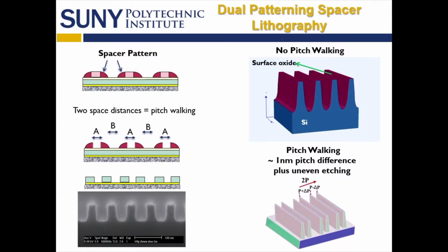So as you can see at the top left, if you make a transistor-type structure, that lighter-colored rectangle is your polysilicon gate, and the spacer oxides are those red-orange curved shapes on each side of the polysilicon gate. If you get rid of the polysilicon gate and use those spacer oxides as a pattern to etch the silicon below, you can get these fin structures.